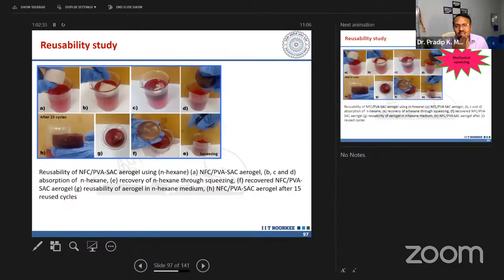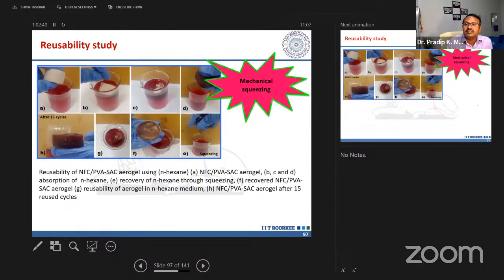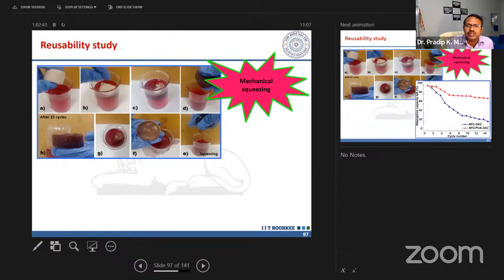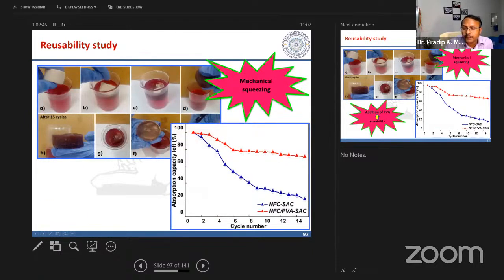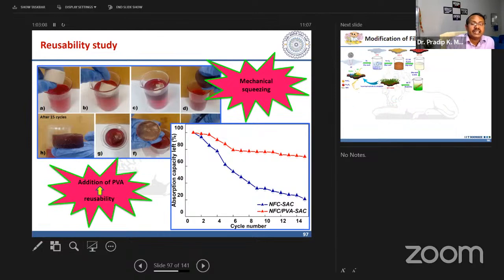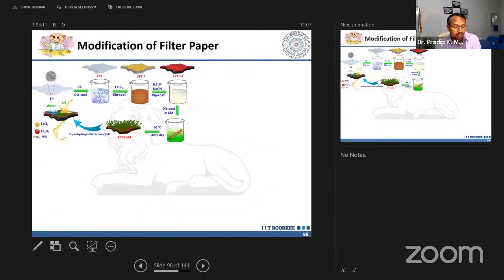And reusability study: whether this material can be utilized many times. We have checked how many times we can do it. Then mechanics, this is the simple mechanical squeeze we try to do. Just after the 15th cycle, if it is not modified, then the capacity of absorption goes down drastically to 20%. But after modification, almost 70% property retention is still there. That is one of the important parameters, that at least many times we can utilize it. So addition of PVA is increasing the wettability with reusability.